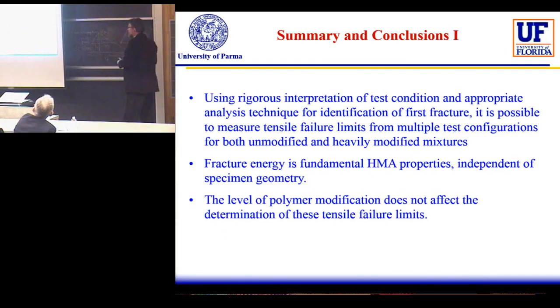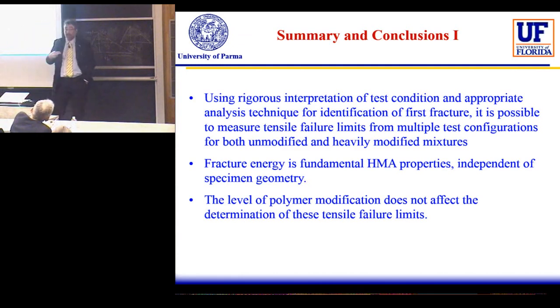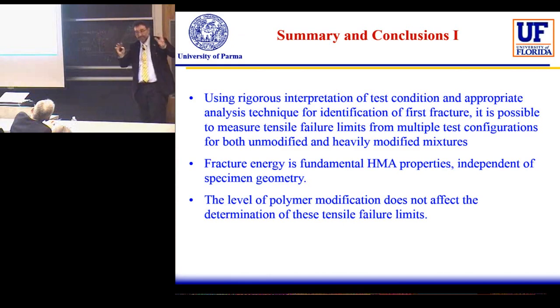So, in conclusion of this part, we can say that using a rigorous interpretation of the test conditions, it's possible to measure the tensile failure limit for different test configurations, and we were able to say that the fracture energy is a fundamental property of the HMA material. In particular, it is the fracture energy calculated following the approach of HMA Fracture Mechanics, which is one of the approaches that you can find in the literature. And the level of polymer modification does not affect the determination of the failure limits.